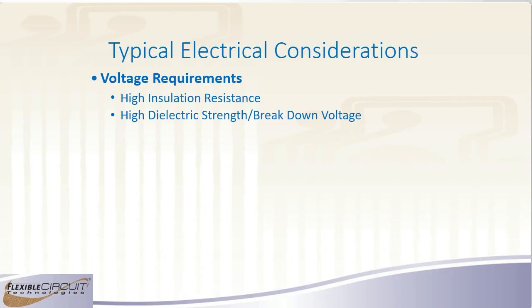The polyimide films are good to almost 5,000 volts per mil of thickness. The thermosetting adhesives are over 2,000 volts per mil of thickness. So you have really pretty good voltage characteristics and isolation characteristics on your insulators. But if you do have high voltage, you do have to take that into account.